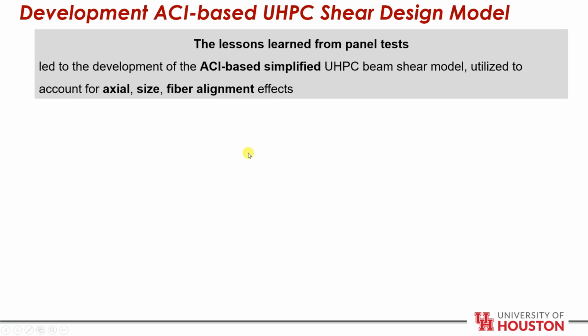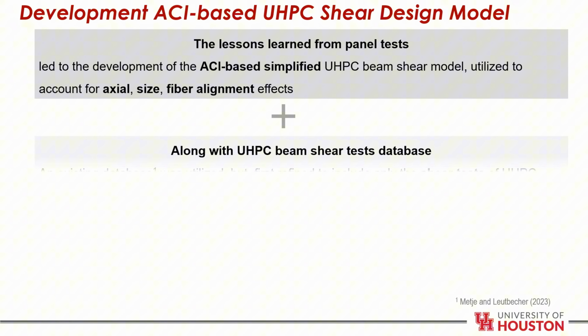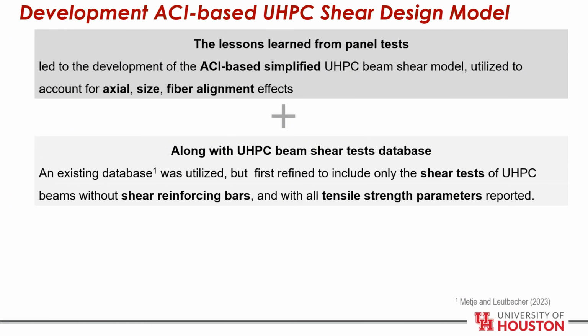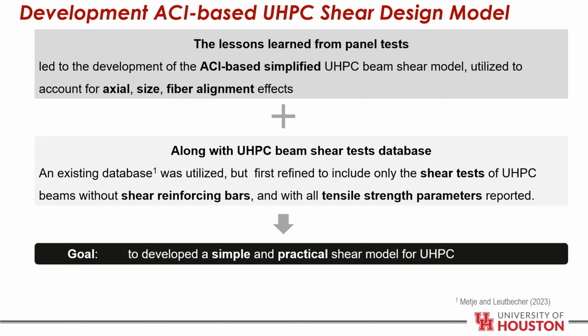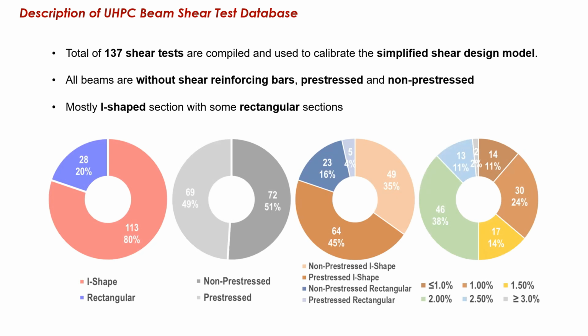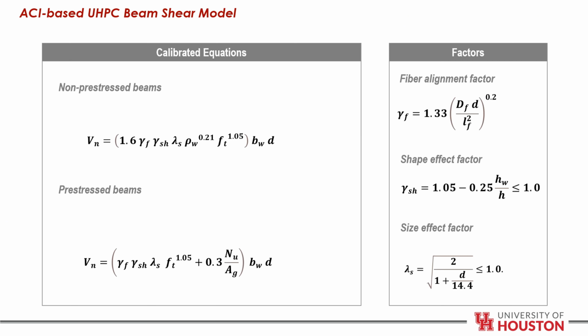From the lessons learned from UHPC panel tests and the calibrated size effect factor, along with the shear database from the literature, a simplified and practical shear model for UHPC was calibrated and presented. The database consisted of I-shaped and rectangular sections, non-pre-stressed and pre-stressed, and the calibrated equations are summarized here. As we can see, 2 equations were proposed for non-pre-stressed beams and pre-stressed beams, and 3 factors were adopted to account for the fiber alignment phenomena in each, the shape factor, and finally the calibrated size factor.